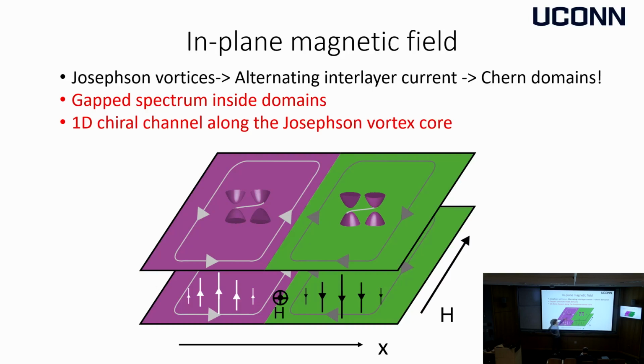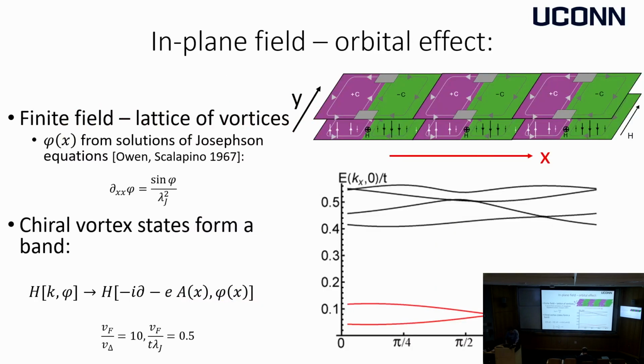So the picture is you will have topological domains. To the left of the vortex is going to have one chirality, to the right of the vortex is going to have a different chirality, but the edge modes coming from these two domains go in the same direction. So they will not gap out, they should be stable. And this is indeed what a calculation tells you.